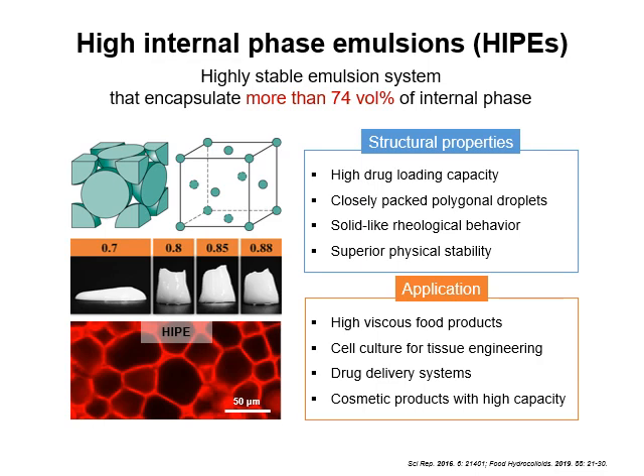First, high internal phase emulsions, HIPEs, contain an internal phase over 74 volume%, and their closely packed droplets form polygonal shapes. Owing to this jammed emulsion phase, HIPEs commonly exhibit a solid-like rheological behavior. Moreover, the HIPE phase is viscoelastic, and consequently the dislocation of droplets is structurally hindered, which renders the observance of either sedimentation or creaming very rare.